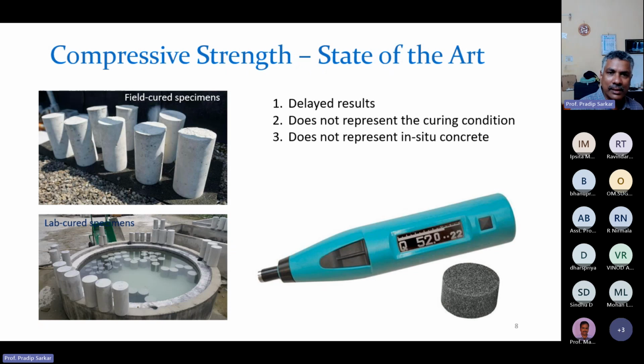Now you see what is the traditional process that we follow. We make cylindrical specimens, and we cure them on the field, or we take them to the laboratory for lab curing, and then we break them at 28 days mostly, or 7 days. Therefore we get a delayed result, so intervention is difficult, right? And it does not represent the curing condition properly, because these are cured in the laboratory under water, but in the actual structure the curing condition is different, right or wrong?